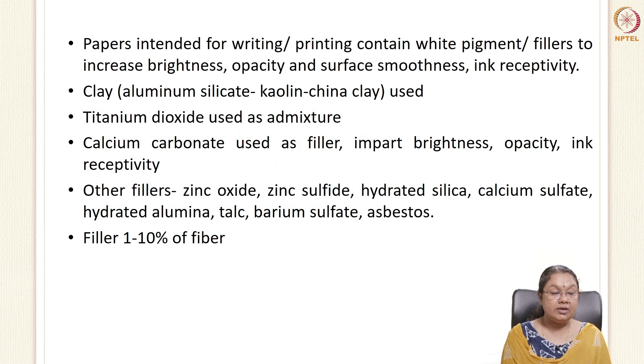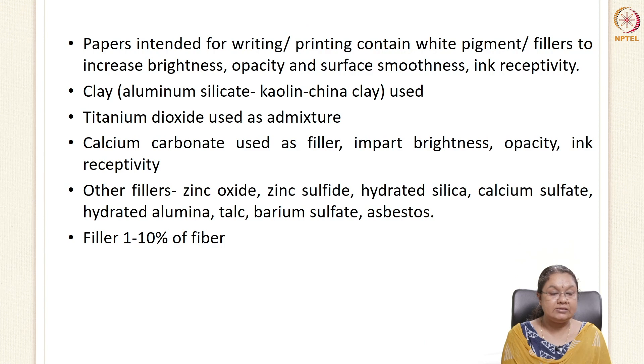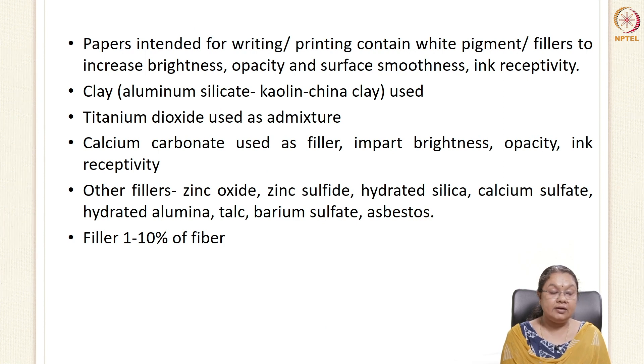Papers intended for writing and printing need brightness, so white pigments or fillers are added during the beating process. Fillers improve brightness and opacity and smoothen the surface, increasing ink receptivity. Common fillers include clay, titanium dioxide, and calcium carbonate, which impart brightness, opacity, and ink receptiveness. Other fillers include zinc oxide, zinc sulfide, hydrated silica, calcium sulfate, hydrated alumina, talc, and barium sulfate. Filler composition is one to ten percent of the fiber.